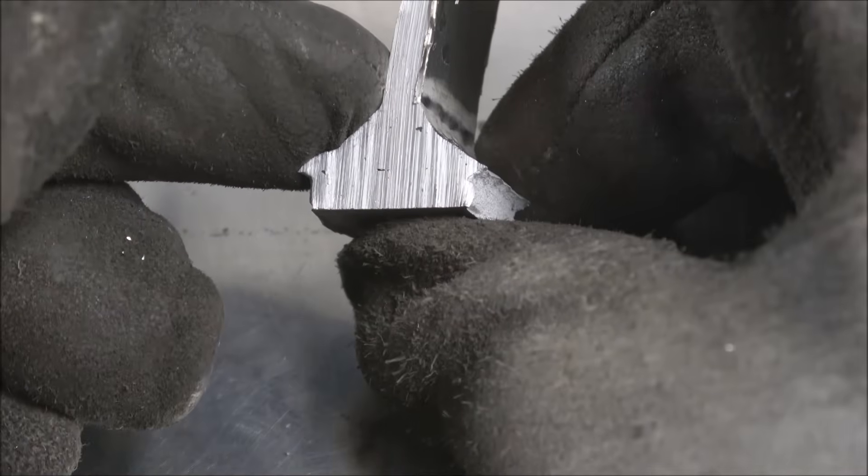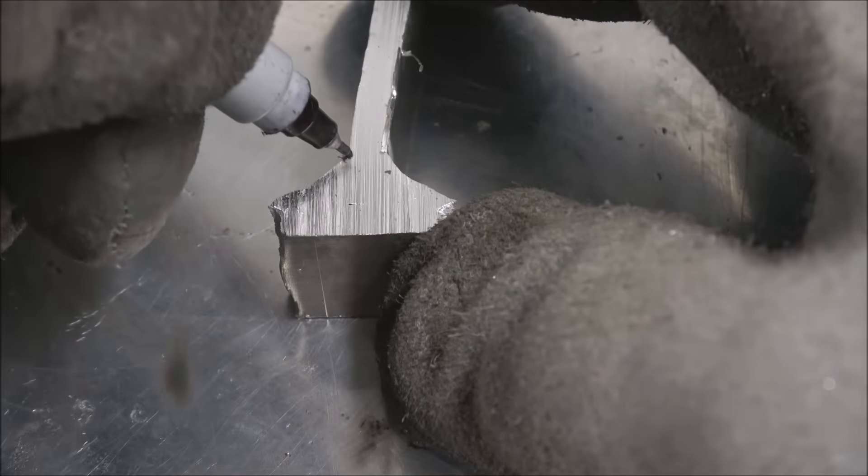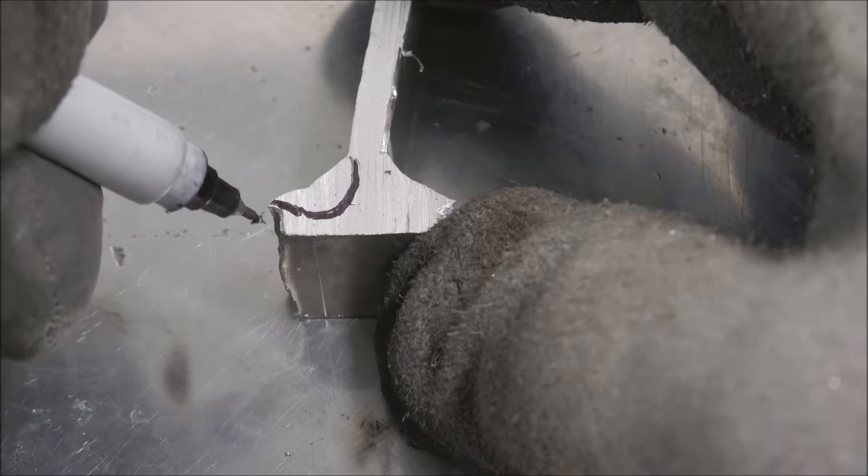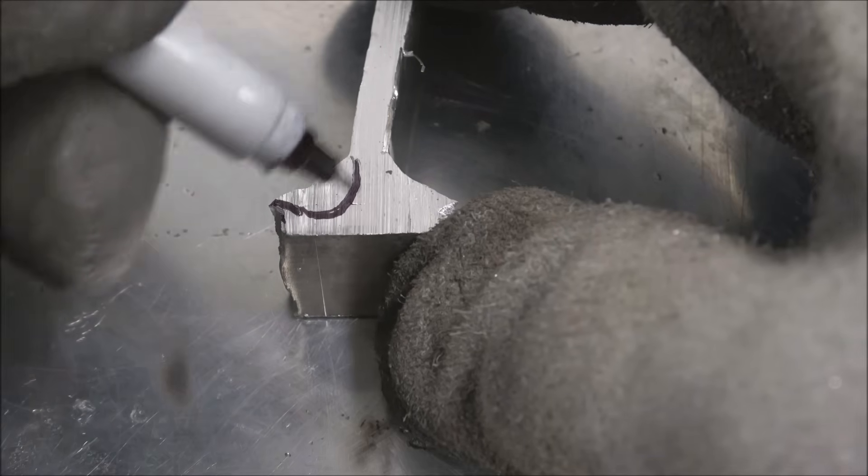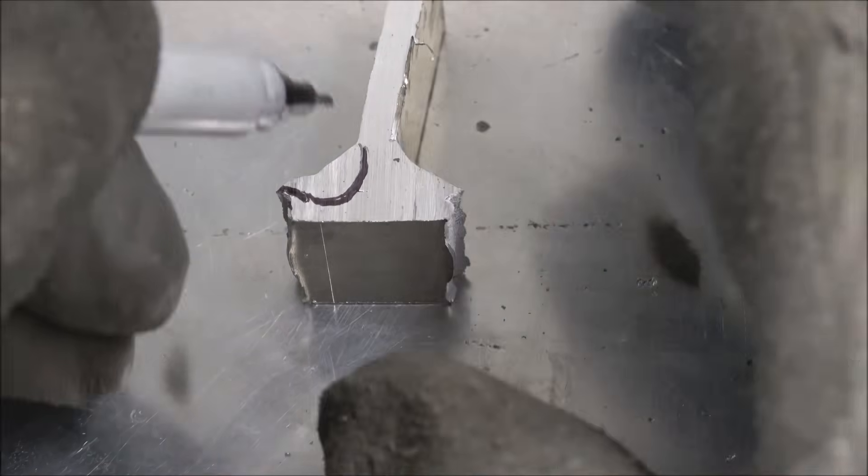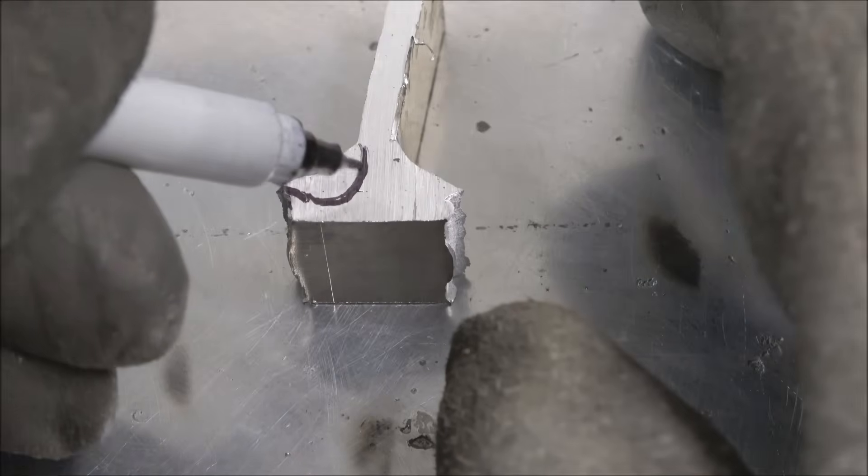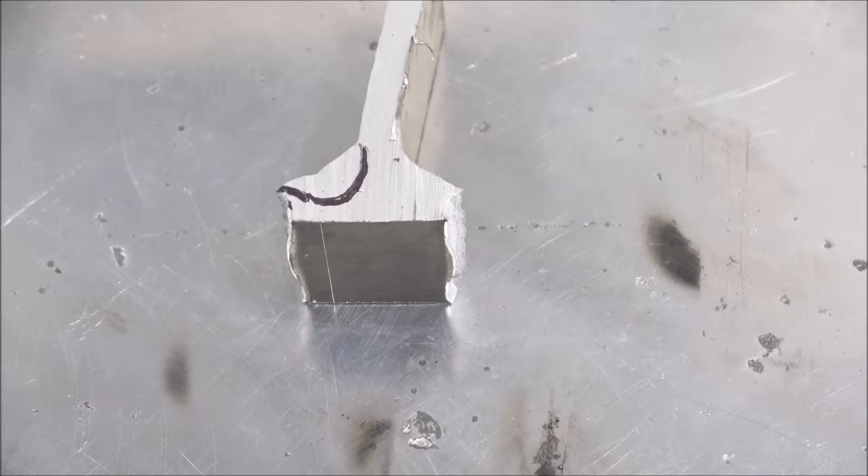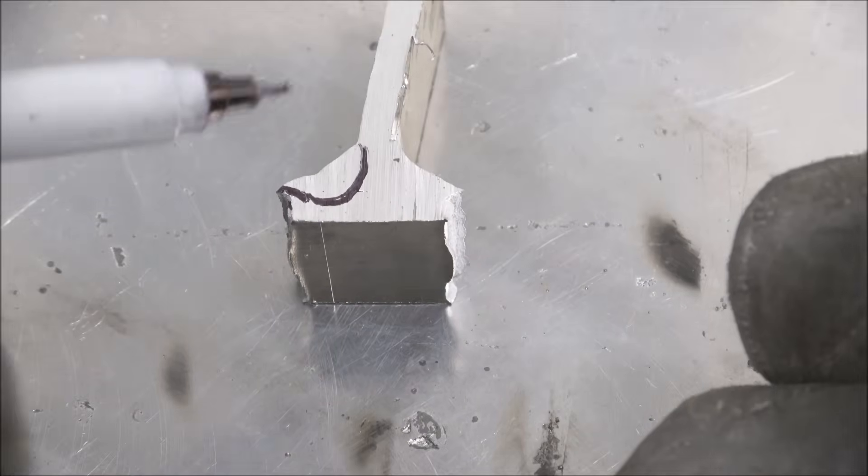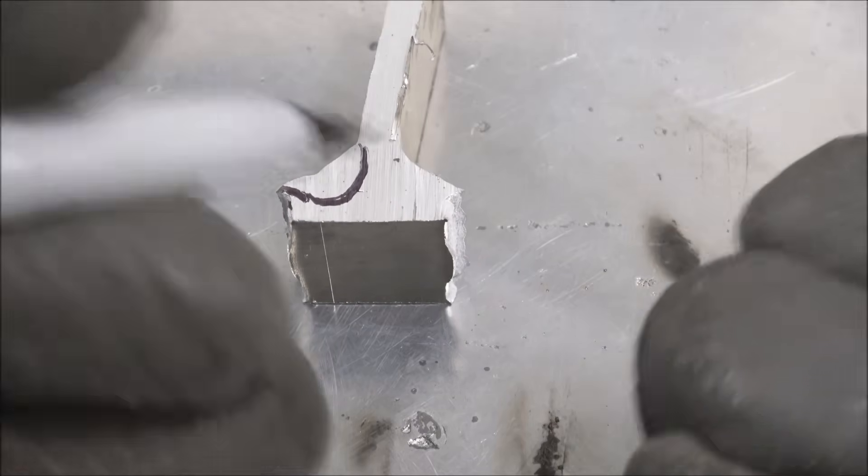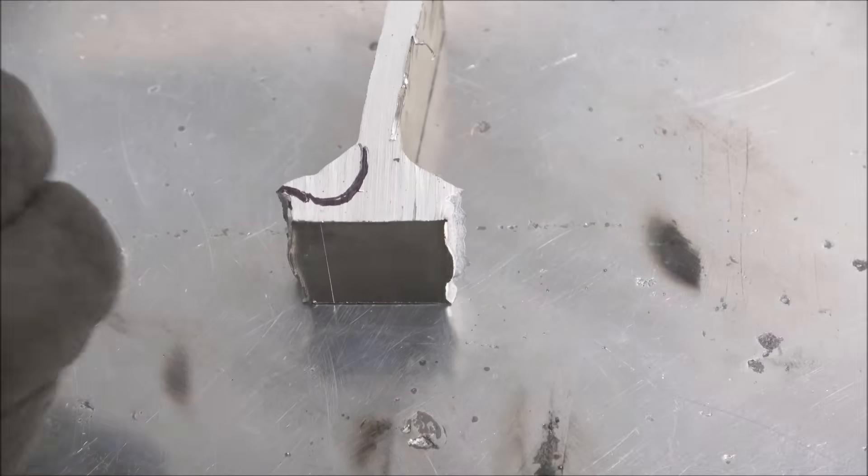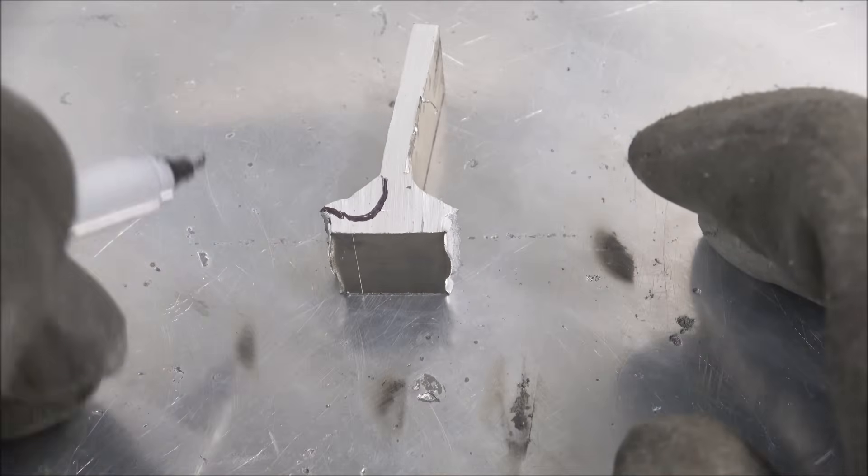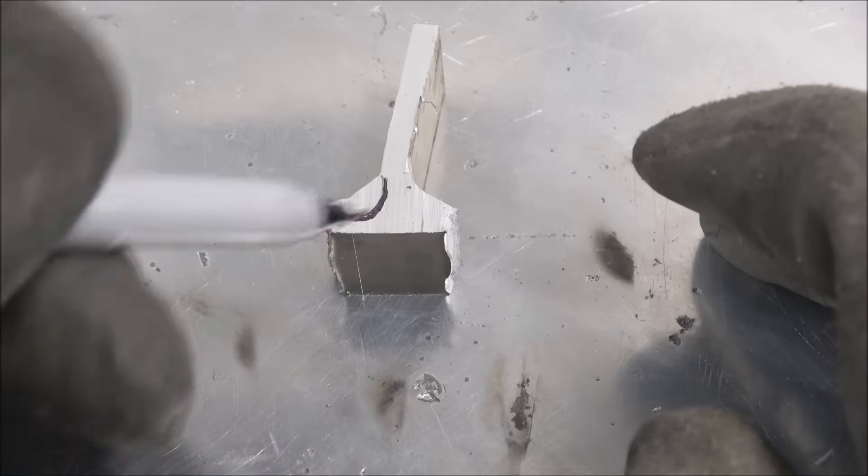So hopefully this is a little bit of a lesson for all you cut and etch nerds out there. This one fused in like this. And it cracked right here outside of that. So this, you know, this could have been huge. And then you can look at a weld and say, oh yeah, it burned in great. Good strong weld. But you don't really know until you actually bend test the thing. Depends on the filler rod you use. Depends on how hot you get the part or if it's too cold. There's just so many variables that you don't get a full understanding just by doing a cut and etch and looking at it to see how it liquefied in.